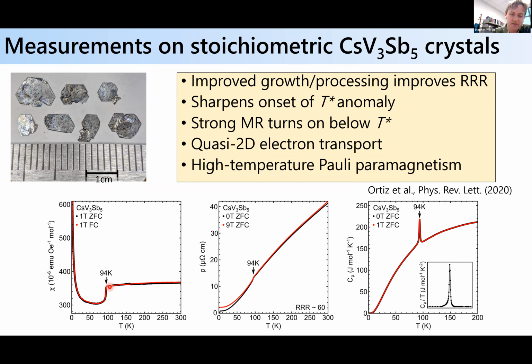You can see in this cleaner material, the high temperature susceptibility is rather flat, very Pauli-like. And then you see a sudden drop as you cool below this T star transition, which is at 94 Kelvin in the cesium system. That's consistent with a gap opening at the Fermi surface, where you're losing some density of states in a Pauli paramagnetic type model. And in transport, under zero field, the black line, you can see there's this kink as you cool through this 94 Kelvin phase transition.